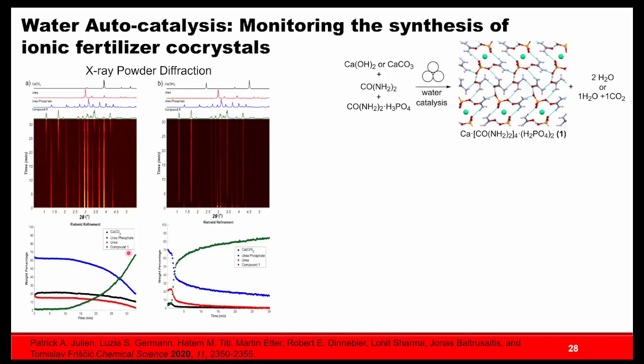But what I'll point you to here is this is the calcium carbonate reaction. When we do the refinement of this data, for us to reach half weight conversion of our co-crystal, it takes 30 minutes for calcium carbonate, whereas we're getting fast conversion in 3-4 minutes using calcium hydroxide. And this really struck us in the data. Why is calcium hydroxide so much faster than calcium carbonate?